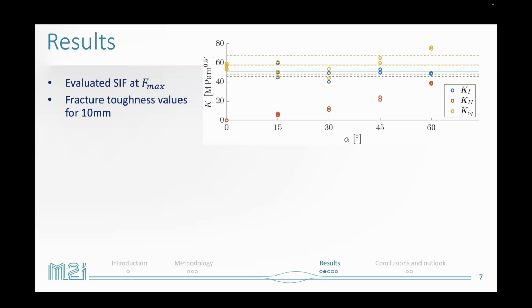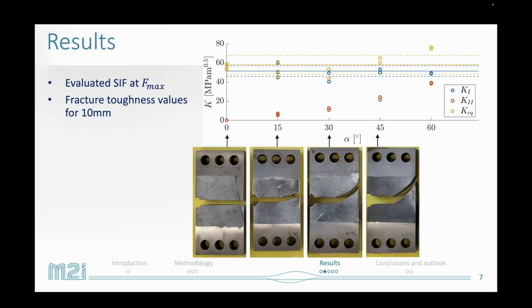And we have the similar line for K1. So it turns out that for these specimens, the specimens for this type of steel, R260MN rail steel, evaluating the fracture condition based on K1 max yields better results. Then we have the corresponding crack paths.